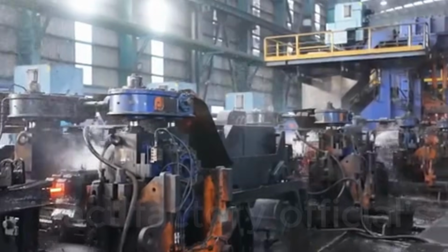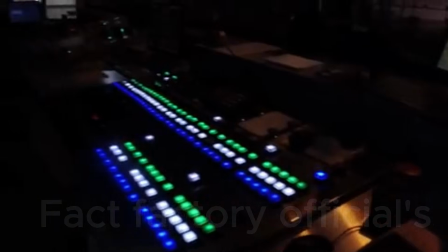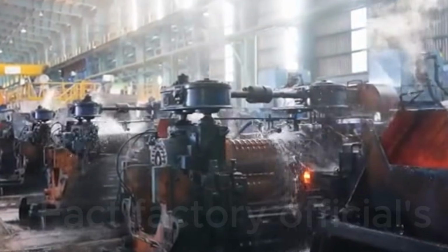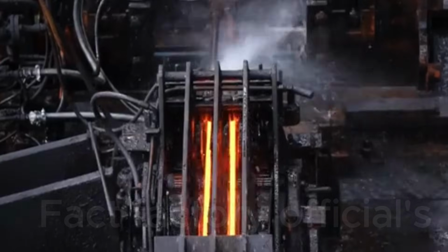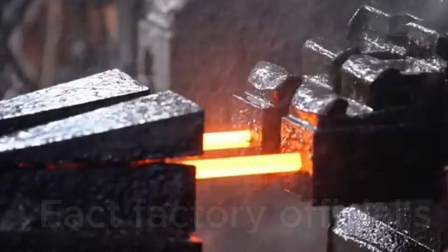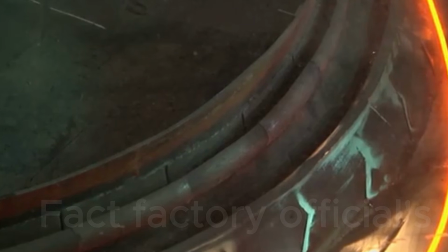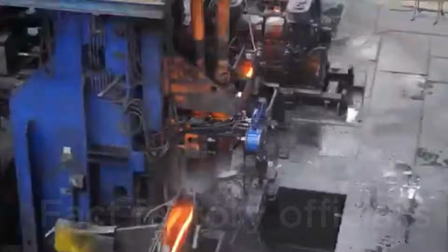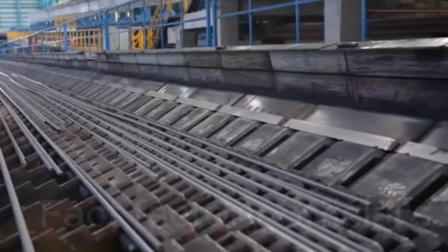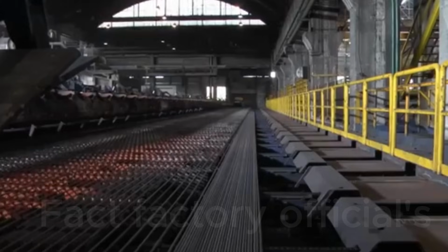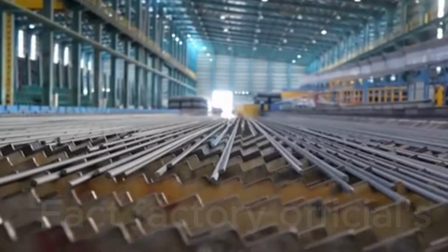Once in the wire drawing stage, the steel passes through a succession of dies with progressively smaller diameters. Each pass makes the wire thinner, the surface smoother, and the internal structure more uniform. This stage is carried out at room temperature, but requires strict control over pulling force, speed, and the friction between steel and die. Even the slightest deviation can cause the wire to break, deviate in size, or lose the ductility needed. In modern plants, laser sensors are installed along the line to continuously measure the wire diameter, paired with automatic feedback systems that adjust the pulling force in real time. The result is high-strength steel wire coils produced with near-perfect dimensional accuracy and the durability required for cable manufacturing.